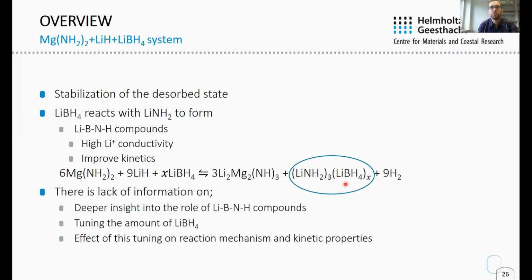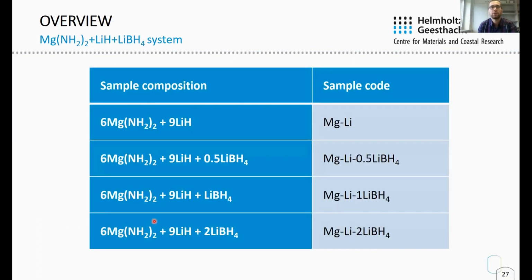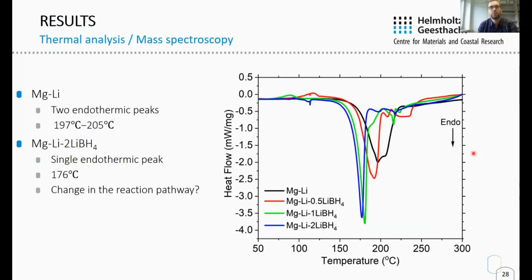Moreover, there is a possibility to change this lithium borohydride to lithium amide ratio and to form different lithium BNH compounds. The effect of this on the mechanism and kinetic properties is not well known yet. In this direction, I prepared the samples with varying amounts of lithium borohydride and used a similar sample coding as before. The thermal behavior of the pristine sample is similar to before.